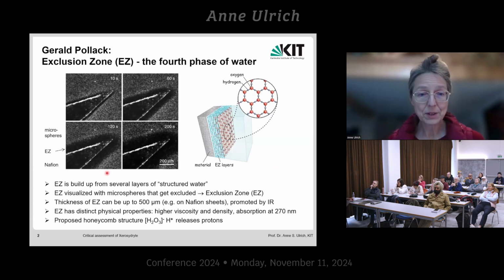And what you see here, that a piece of polymer or any other material, when it is immersed into a solution or suspension of small plastic microbeads, forms a thin layer on its surface, which grows here as a function of time and becomes visibly thick, up to 0.5 millimeter. And this is a genuine phenomenon which Jerry has tried to explain in terms of a model of honeycomb layered water molecules, which I doubt, but in the end, it's only a water model of a permanent structure, which is something Paolo told us not to believe in.